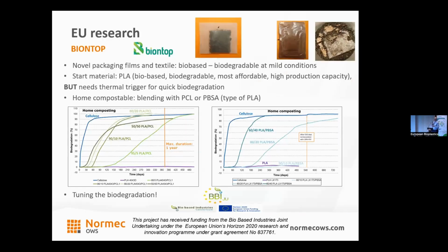This is, of course, the BIONTOP project, which we like very much, and it had the goal to develop novel packaging films and textiles. We wanted them to be bio-based and also biodegradable at mild conditions. As also mentioned by Raoul, our start material was PLA. Why? It's bio-based, it's biodegradable, and at the moment also mostly affordable, and quite high production capacity is already available. But we know that PLA needs a thermal trigger to start degradation. And in home compost conditions, you don't have these high temperatures. You only work at 28 degrees as defined by the standards.